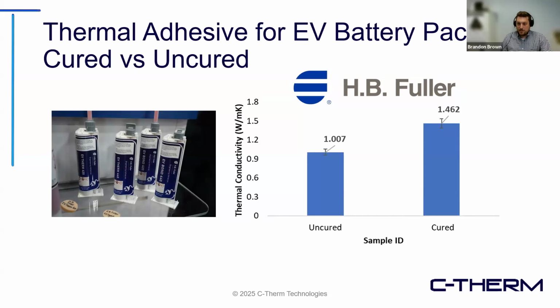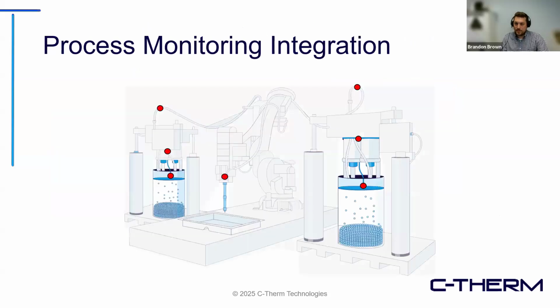There are many methods that can measure fully cured samples because the samples are quite stable. You can make the sample, cure it, easy peasy. However, uncured, you want to have very quick data acquisition. It's very important if you're trying to measure something before the curing process occurs. We've generally seen an upward shift in thermal conductivity in many of the adhesives that we've tested as they cured in the past, and this was also the result found here. Next slide, please.